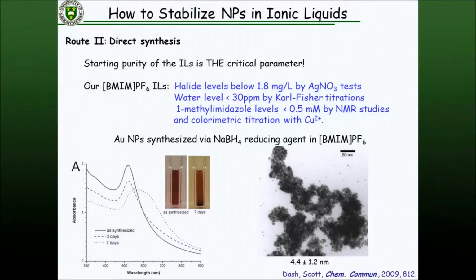And here's the idea then: as synthesized in ultra pure ionic liquids, very low halide levels, very low water levels, and we've essentially taken methylimidazole levels down to below the detection limit by NMR. We make them, and then over time you can see a little bit of precipitation in 7 days. The particles slowly start to precipitate out, and you look at the electron microscopy image over time, and you see the larger aggregates of particles that are precipitating out. If you go in, though, and you add in the methylimidazole starting material at very, very low levels, 1 millimole, barely detectable by NMR, all of a sudden, you get magical stability again.